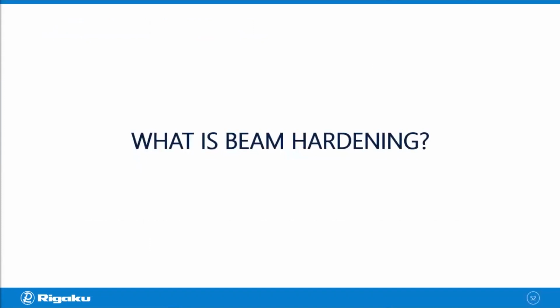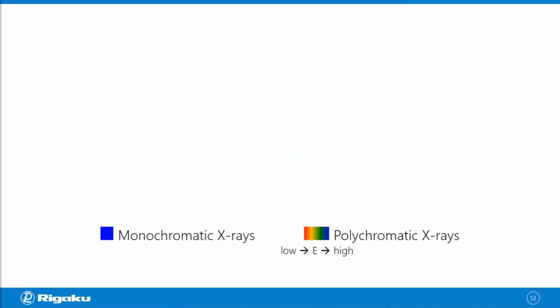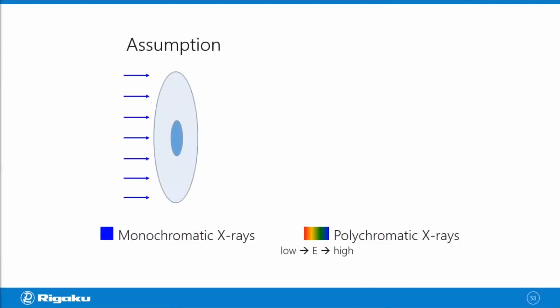So what is beam hardening? To explain what it is, I'm going to use solid blue to represent monochromatic X-rays, the single energy X-rays. And I'm going to use rainbow colors to represent polychromatic X-rays. They have a range of energy. And the artifacts based on beam hardening come from the difference between what we assume in the reconstruction calculation and what we actually do when we do experiments. The assumption we're making is, you have a sample and you have monochromatic single energy X-rays coming in, and they get absorbed by the sample and come out again as monochromatic single energy X-rays. This is the assumption we are making.